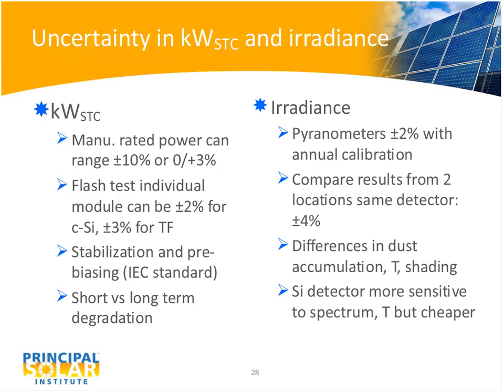Similarly, the best that we expect to get from flash testing of individual modules with a well-calibrated system, with a calibrated module, is on the order of plus or minus 2% for crystalline silicon, and the very best you could expect for thin film is probably going to be on the order of 3%. And that's because there's some stabilization or pre-biasing steps that are required by the IEC standards. That's the International Electrotechnical Commission. For the thin film modules, before they're tested, they should go through this brief regime of stabilization or light soaking.